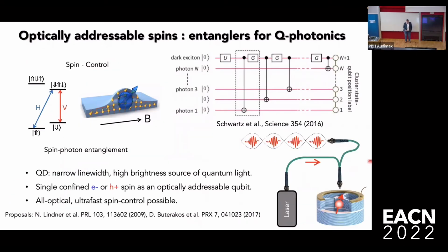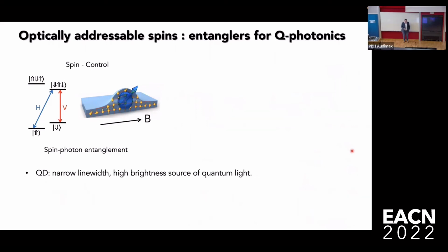I wanted just to spend a couple of minutes talking about spins and molecules, because this is an area where I think there's a lot of, let's say, potential for the future. Maybe if I go back, I showed you already at the beginning of my talk this picture, which shows a typical scenario for trions in a quantum dot: a single spin, where an applied magnetic field splits the spin states into two spin levels, and you have a lambda transition to an excited state trion. In this case, for Voigt geometry, it's horizontally and vertically polarized. That allows you to generate spin-photon entanglement by preparing the spin state optically, scattering photons from the spin state, and having a polarization state which is then dependent on the spin state in the system.